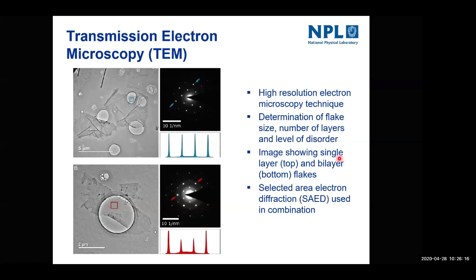And as we can see here at the top, looking at single layer graphene flakes and bilayer graphene flakes, you can understand what the flake looks like and the lateral size, but you can also understand the number of layers by looking at the diffraction pattern, which is a very, very powerful technique in that respect. But again, with microscopy techniques, we will need to look at a statistically relevant number of particles, flakes, to get a good understanding of the material.